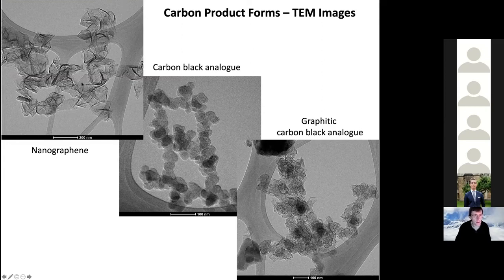The most interesting product is the nanographene. You're seeing that as crumpled layers. Many of them are somewhat concatenated together, something like a Russian doll from that concept. But many are wrinkled, few-layer stacked nanographene, versus a product that is somewhat more amorphous or maybe more graphitic, both resembling carbon black. And you can see that there's a strong difference in the internal structure within the particles in the lower image on the right. They're not uniform in contrast nor filled uniformly within, but there's a considerable amount of semi-graphitic structure within